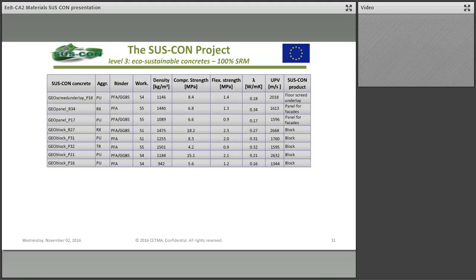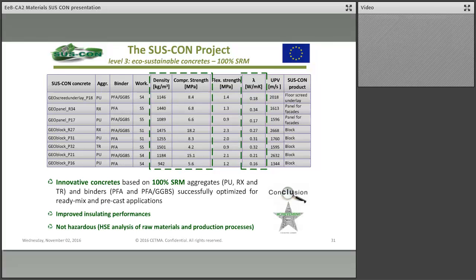These are the main results we have obtained on the Suscon products. Very good results were obtained both in terms of compressive strength, up to 18 megapascal, and thermal insulation properties, that is 0.16, the lowest. So, innovative concrete based on 100% secondary raw material from both the aggregates and the binder side were successfully optimized for ready-mix and precast application and resulted with improved insulation performances, and also resulted as not hazardous after an HSE analysis of raw materials and both production processes.